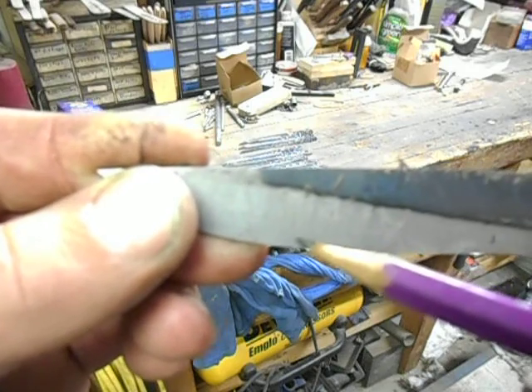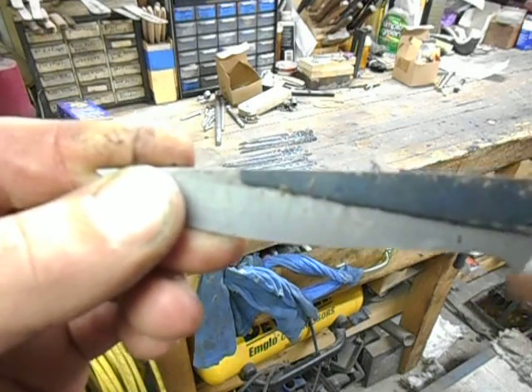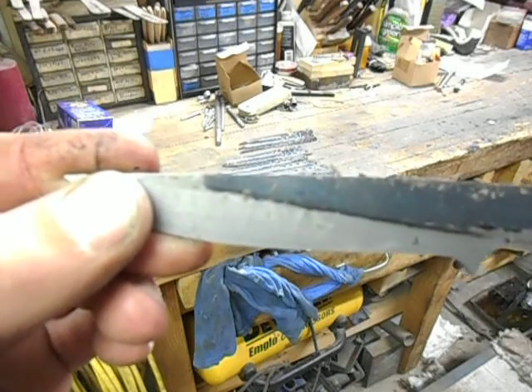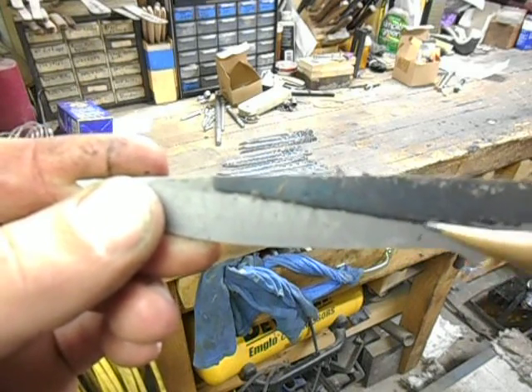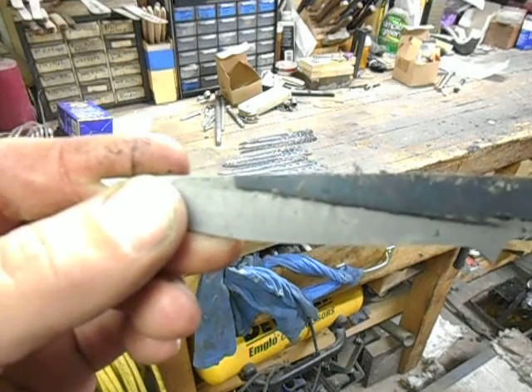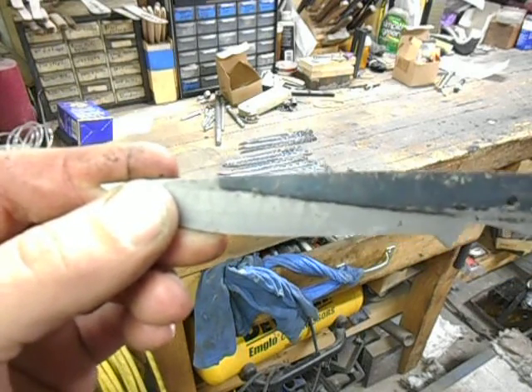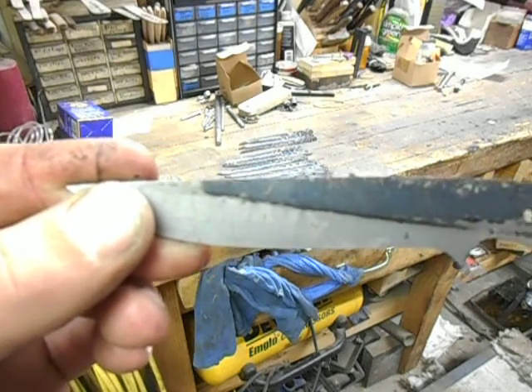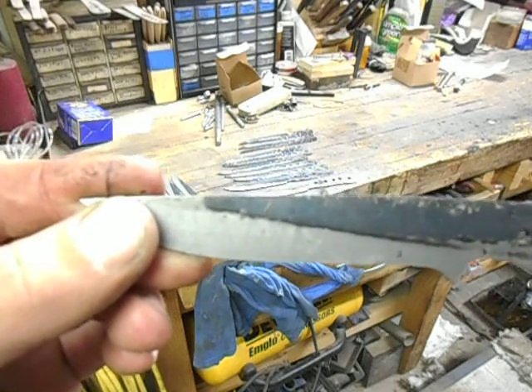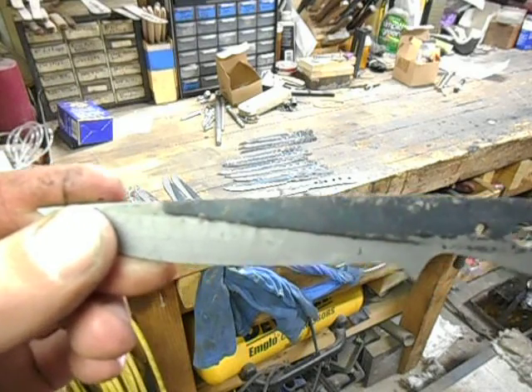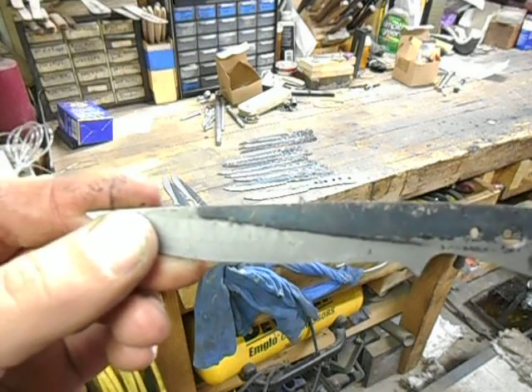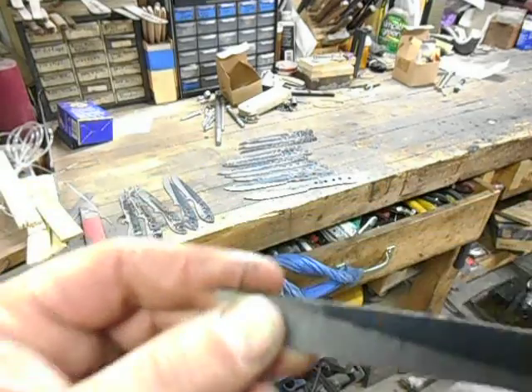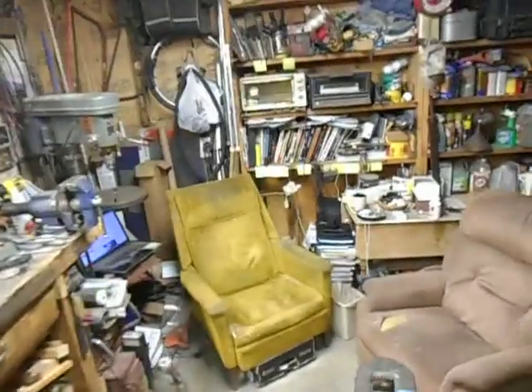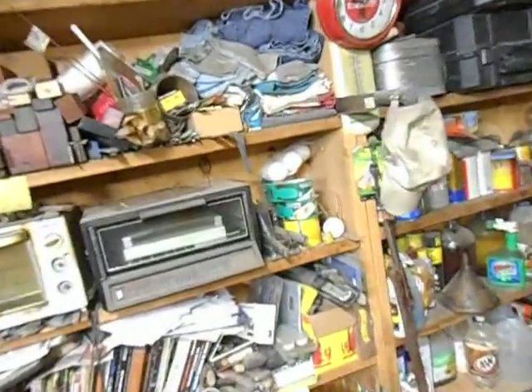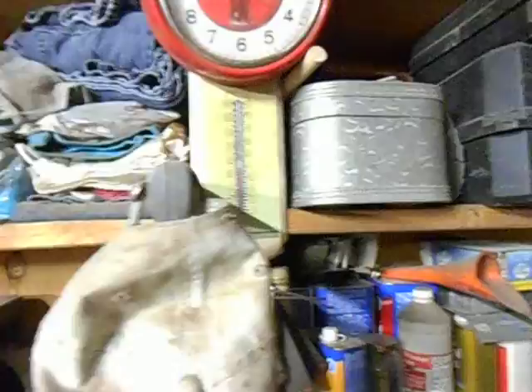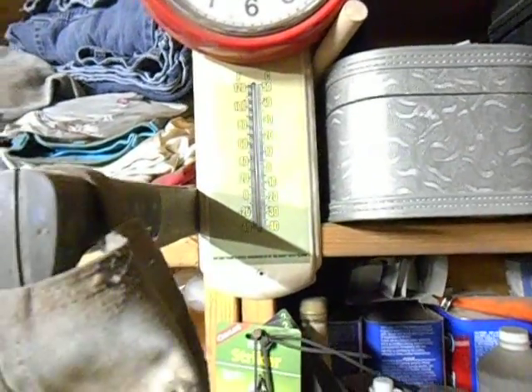More than likely what's happening is that you heat this blade up in the kiln or in the forge, either way. While that blade is in a nice warm kiln, we'll just go with that for this example, it's at a nice toasty 1500 degrees Fahrenheit. You're going to put it into 140 degree canola oil, or if you're going to use Parks or whatever. But like the temperature inside my shop right now, actually let's go find it. I'm going to guess we're at about 50, 60 degrees Fahrenheit. We are at 49.